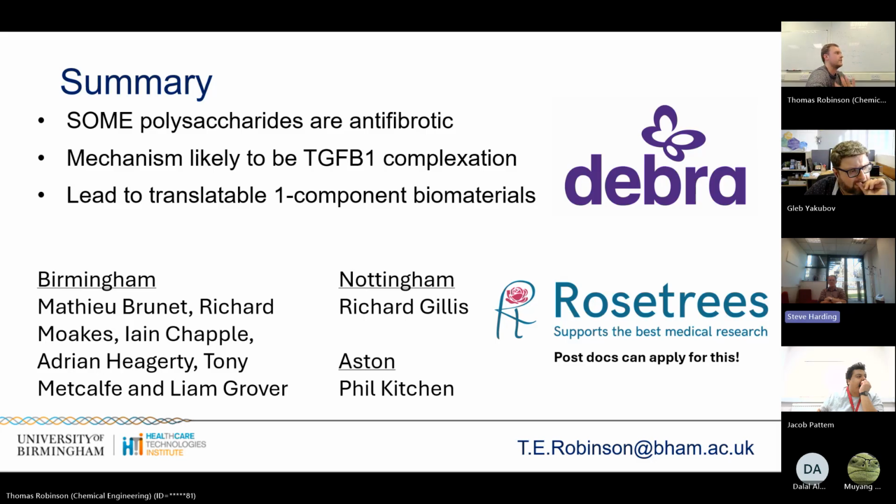I didn't put it in this presentation because it isn't carrageenan, but we showed it with an alginate acetic acid system, which was quite neat. That was for burn wound infection prevention, because acetic acid is quite a good antimicrobial. By increasing the acetic acid concentration, so increasing the overlap, we got better spraying and also massively increased viscosity and viscoelasticity, of huge orders of magnitude, which is really exciting. So we can get both at the same time, which was previously pretty unheard of, because previously viscosity goes up, sprayability goes down, and that's essentially that.